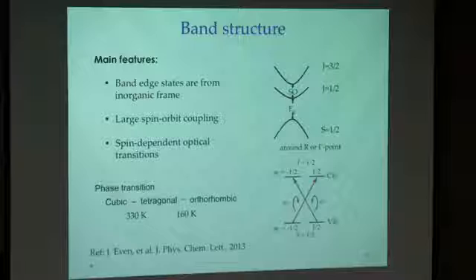To simplify that picture, we have an S-like valence band and P-like conduction bands. They split because of the spin-orbit coupling. Now we have J of 1/2 and J of 3/2. The band edge states are the J of 1/2 conduction band and the S 1/2 valence band. Because of that, with circularly polarized light, we can choose to excite only specific transitions. With right circularly polarized light, we excite from negative 1/2 to positive 1/2. With left circularly polarized light, we excite from positive 1/2 to negative 1/2. That change of angular momentum of 1 comes from the photon.